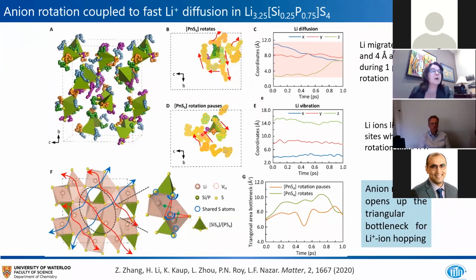In moments where that rotation is transiently paused in the dynamics, the lithium motion is completely static. So it's correlated with this translation when it rotates, and it's correlated with no translation, in fact static behavior, when the anion is paused. And the reason for this coupling of the motion of the polyanion with that of the lithium is simply because of the structural effect.